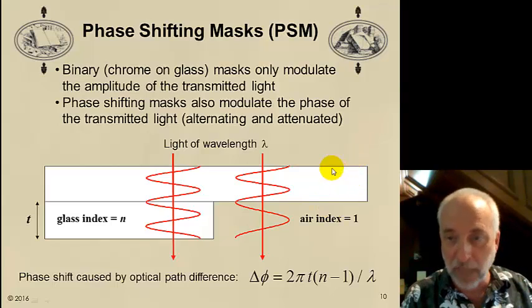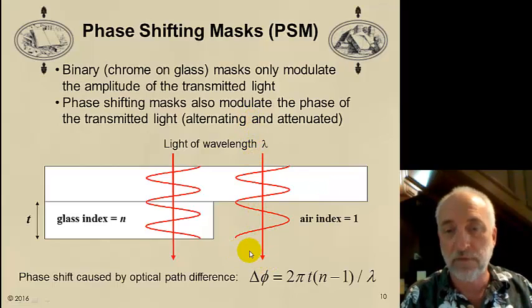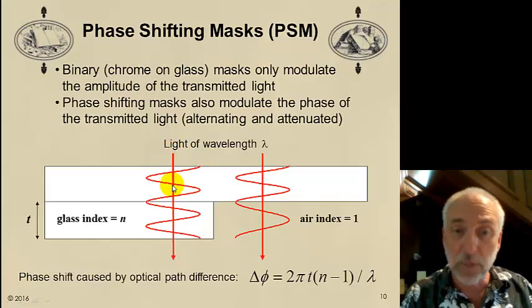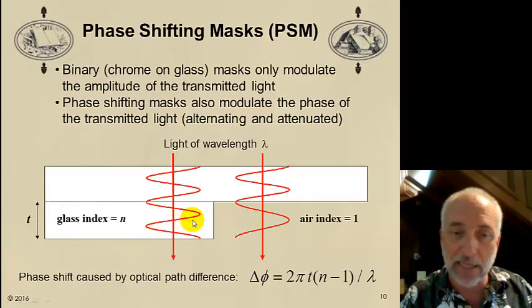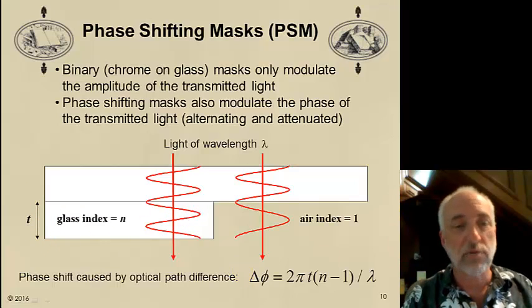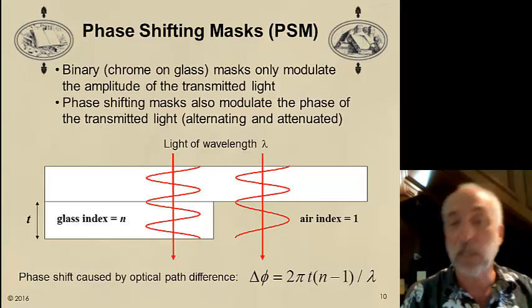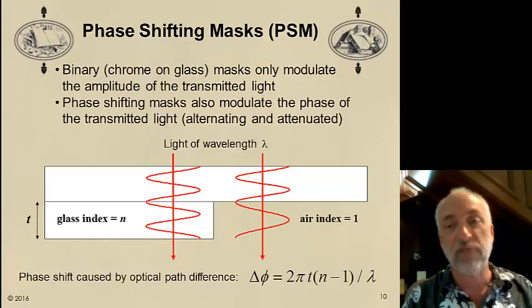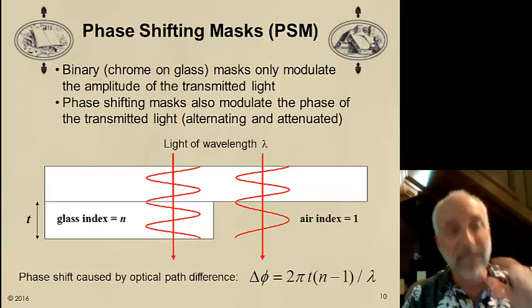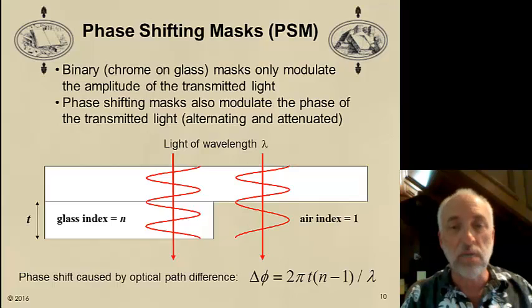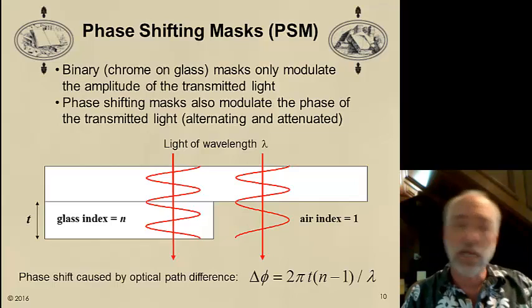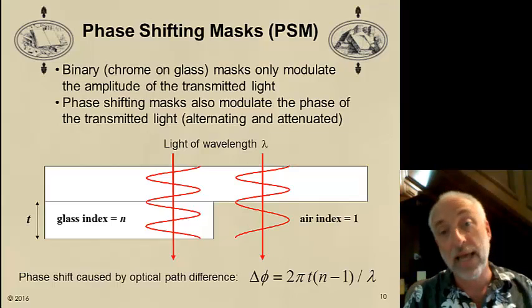So here's a mask blank over here. I have light going through it, and it comes out at a particular phase. Next to it, I have light going through that same blank, but on top of the blank, I pile up a piece of glass of thickness T. Now, the glass has a refractive index of n, typically 1.5. The air has a refractive index of 1. So as the light is transmitted through that thickness of glass, thickness T, it's undergoing a phase change upon its travel through that glass.